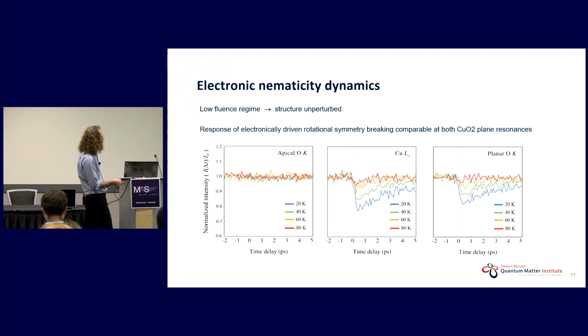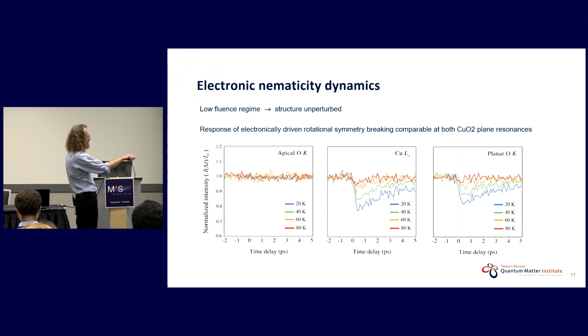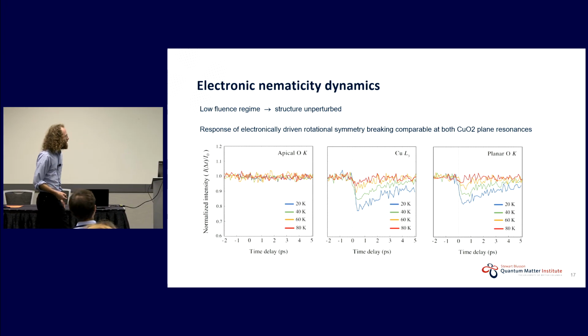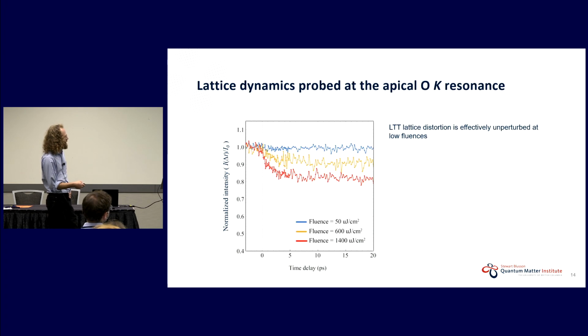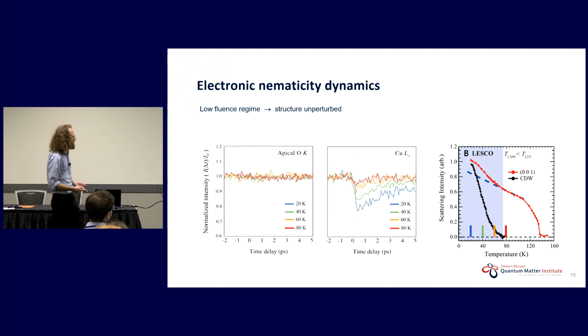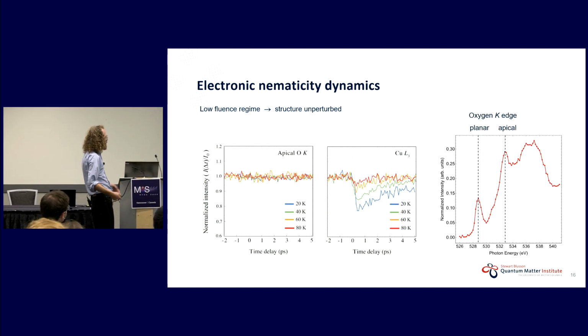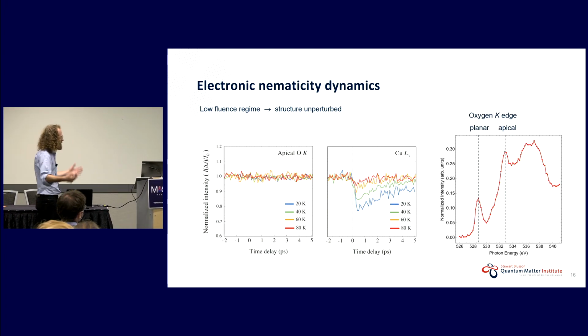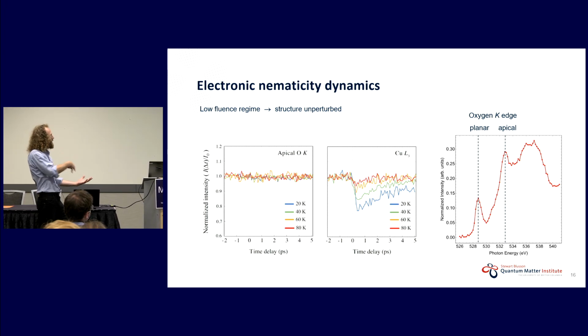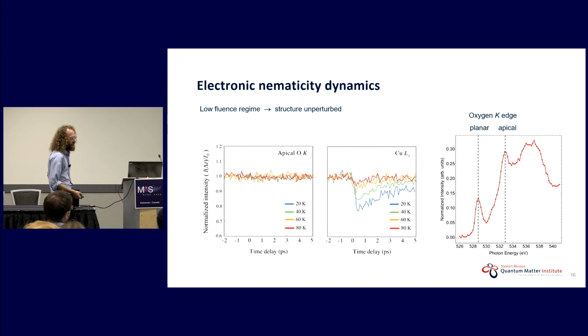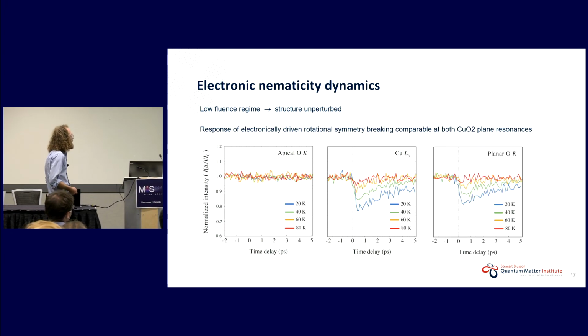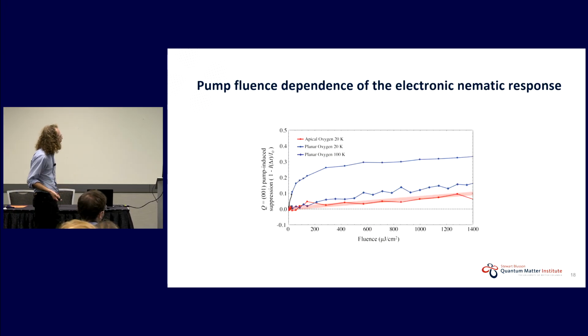And the other thing that I want to point out is that the recovery time scale, which is similar to what is seen in the CDW, is also sort of the same as what we see as the suppression time scale of the lattice. So in my mind, naively, I'm going to say, okay, we're heating up, exciting all these hot quasi-particles, which are coming out of the CDW phase. And as they couple to the lattice and heat up the lattice, destroying the LTT, they then condense back into their CDW, okay? This is sort of my naive picture. And what do we do then?